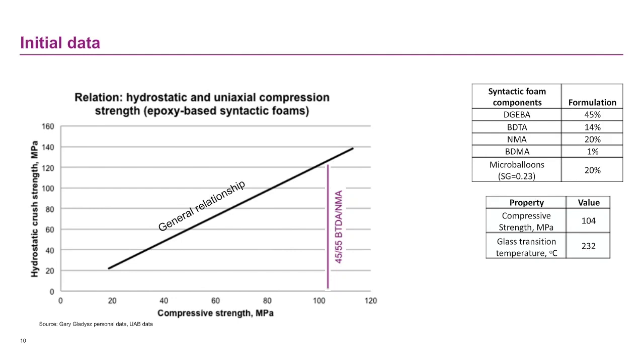And if you further correlate those with in-service depth, which can be done, that comes out to about 34,000 feet. Which is well beyond the 15,000 feet that we've been using as a house figure so far in the discussion. So the potential for these blended systems to far surpass the current state of the art is clearly demonstrated here and illustrated, especially by the glass transition temperature, which was obtained here, which is 232 C. Clearly a good 20 to 30 degrees higher than anything that is conventionally in use.